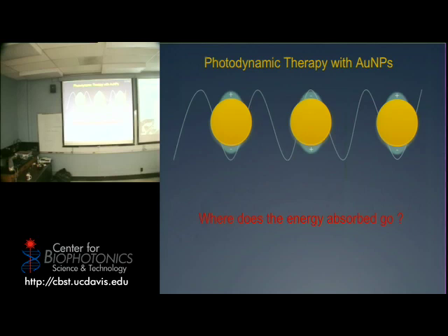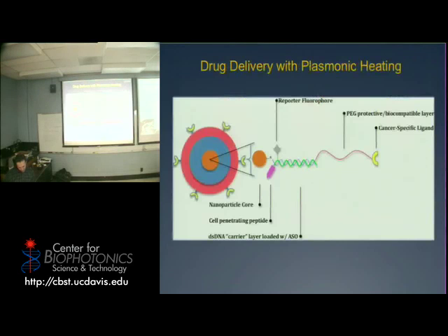Come on, guys. This is easy. Heat, right. You have these electrons that are just moving back and forth, and they hit things along the way, possibly. It's essentially kind of like a nanoscale friction. It's not really friction, strictly speaking, but it can be seen that way. So the particle heats. And when I say heat, I'm not saying heat like warm up. They heat up by hundreds of kelvins. They can melt under the input. And obviously, the more intense the light source is, think about a laser, the more intense the heating is.